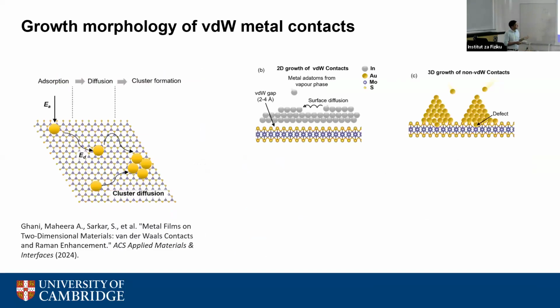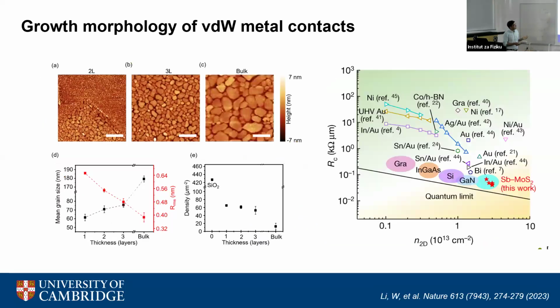So people showed that with bismuth and antimony, people have almost hit the quantum limit for contact resistance. But our case was not that low. We had a certain finite resistance because the gap was around 3 angstroms. And we were thinking, what else can this be useful for? So we have now made a contact where there is a gap between the metal and the semiconductor.